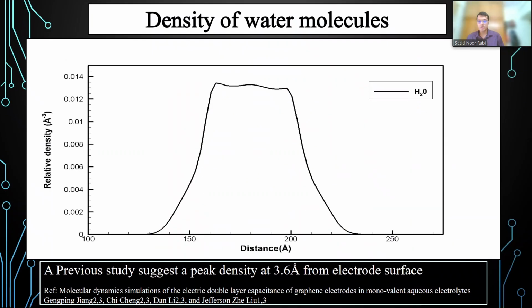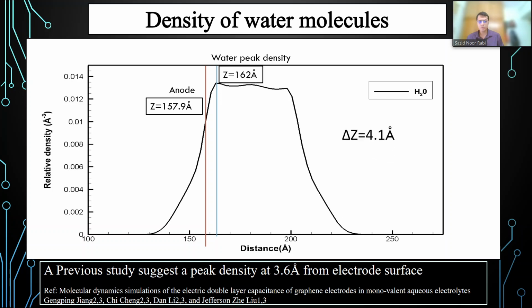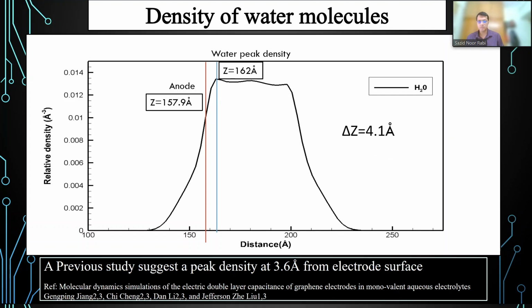We have compared previous studies with conventional planar graphene electrode and found that the peak density is 3.6 angstrom from the electrode surface. In our study, we have found that to be 4.1 angstrom, which is close to that.